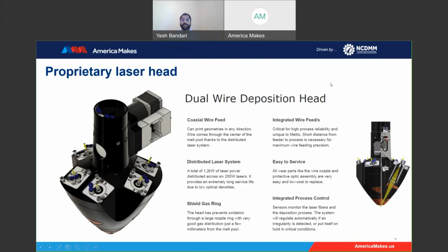So how are we able to get to these good surface finishes and high efficiencies? This is because of the proprietary laser head developed by Meltio. This is where all the black magic happens, and let me tell you some unique features of this dual wire deposition head. The first feature is that the wire comes out coaxially. So you've got wire feed nozzles and then off-axis lasers as well. Having this coaxial wire feed will make the user's life very easy, so that the directionality issues are completely eliminated.